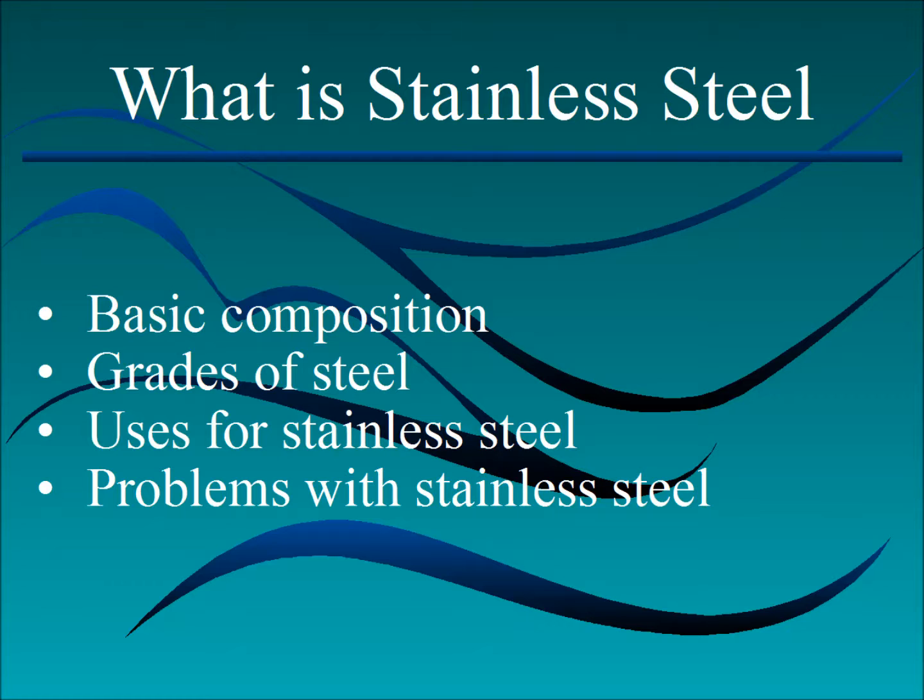The big problem with stainless steel, though, obviously, is that since it is still mostly iron, it can still rust and corrode. Sometimes because the surface has been contaminated by an external source of iron, often during the manufacturing process or during the transportation, or if the surface has been stressed with chlorides and other chemicals, chlorides coming from swimming pools, ocean environment, cleaning the surface repeatedly with bleach, that type of thing. There's a lot of things that can stress the surface.